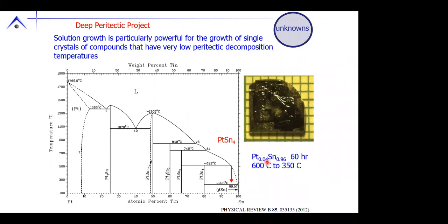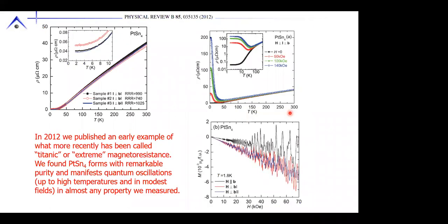Okay, so PtSn4, we can grow out of greatly excess of tin. Okay, so 4% platinum and 96% tin, heat it up, cool it down. This is a fairly quick grow. You know, it's over the weekend, and you get beautiful crystals. And what we found out is this is a material that is incredibly generous. With very little effort, you can form a material that has remarkably high purity. This is a material that has residual resistivity ratios, the ratio of the room temperature to the low temperature resistivity, that can exceed 1,000, all right?